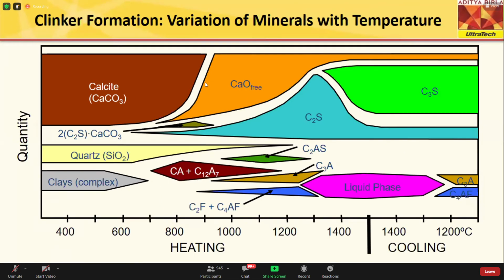Yes, this is one very important slide, clinker formation at various temperatures. I would say, initially at around 600 to 800 degrees Celsius, from calcium carbonate, carbon dioxide escapes out. The process is called calcination, and the lime available is called free lime. During this period, many other processes also take place, like formation of ferrites and aluminoferrites. This free lime reacts with silica and forms. Okay, I will explain this slide by slide because this is a bit complicated slide.